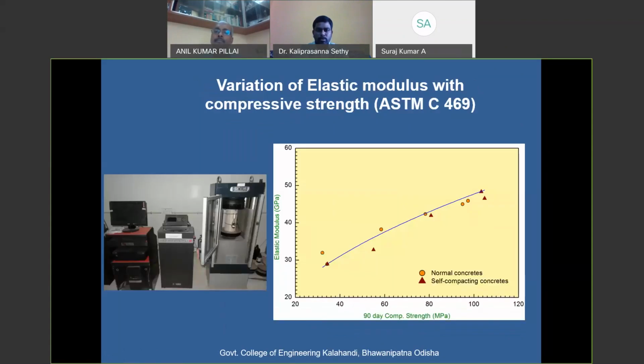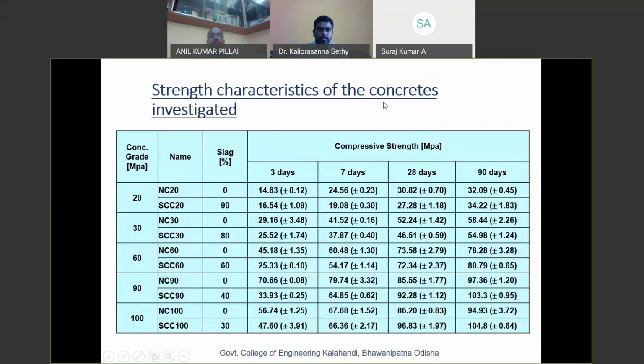And for elastic modulus also we are getting very good results. You can see this is the curve plotted between strength and elastic modulus. This is also showing a very good result. It is showing more than 40 GPa. And here are the strength characteristics which we found for our strength by using the CTM machine. From this you can see there is a very negligible or very minimum deviation for all the samples which we have tested for the compressive strength.